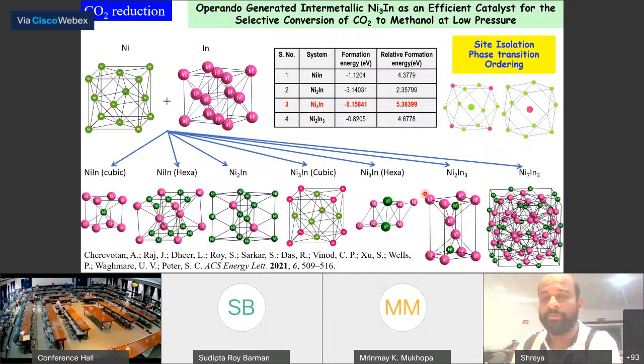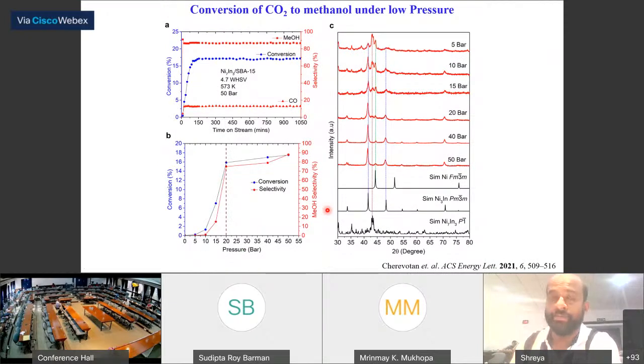XRD will tell what kind of atomic arrangement. So what we did was synthesize, and eventually it ended up as nickel 7 indium 3. Indium is famous for methanol production, and nickel is famous for good adsorption of the CO2 molecule. We probed this in our CO2 reduction facility, and it gives very good conversion in the range of 18% to 20%. The best part is that we could reduce the pressure from 50 bar, which is the state of the art performance at the current scenario, down to 20 bar.